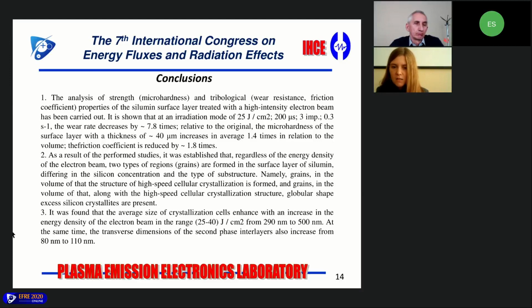And also, it was found that the average size of crystallization cells increases with an increase in the energy density of the electron beam in the range of 25 to 40 joule per square centimeter, from 290 nanometers to 500 nanometers. And at the same time, the transverse dimensions of the second phase interlayers also increase from 80 to 110 nanometers. And that's all.